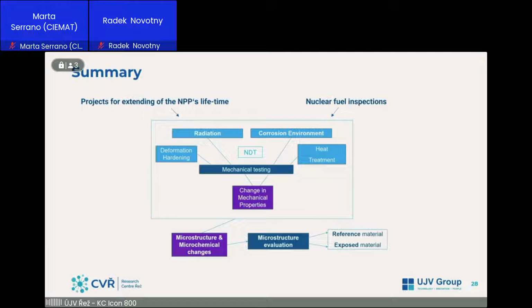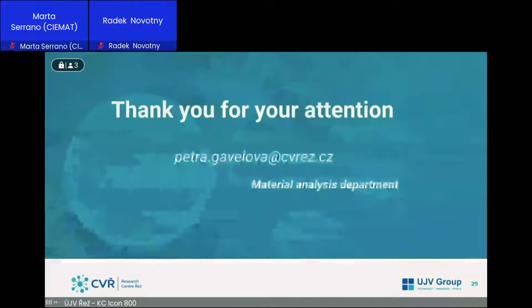So if I give a brief summary of our research on zirconium claddings, we do non-destructive testing as well as destructive testing, and we evaluate the influence of neutron and gamma radiation, corrosion environment, heat treatment and deformation hardening. We do the mechanical testing and observe the change in mechanical properties, and then we research the microstructure and microchemical changes, incorporating them with the mechanical testing group. Then we compare the reference and exposed material. So this is our experimental support of the company. And I would like to thank you for your attention, if you have some questions.